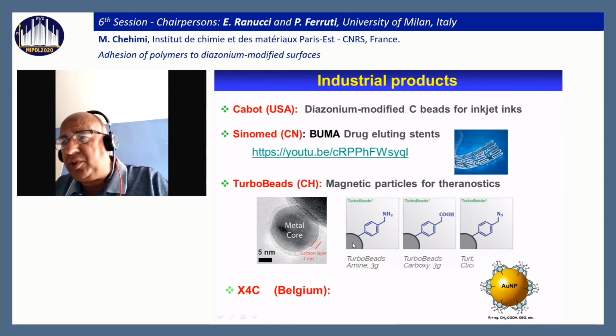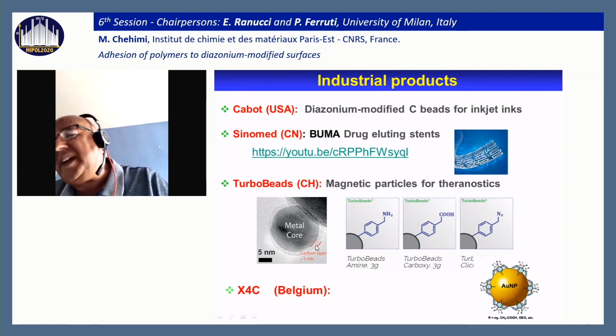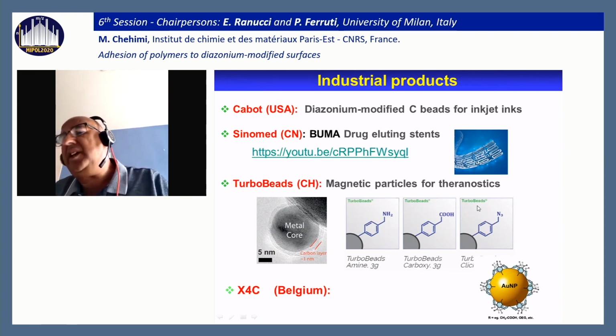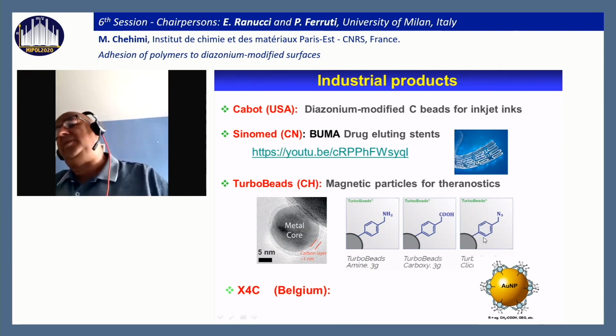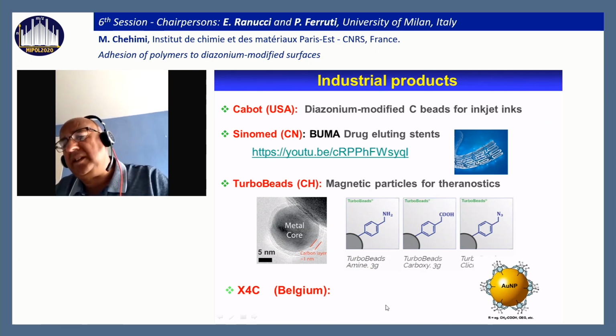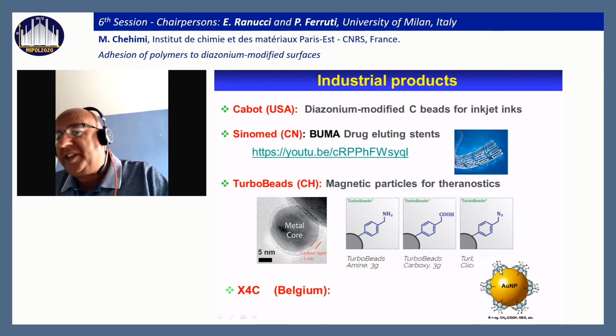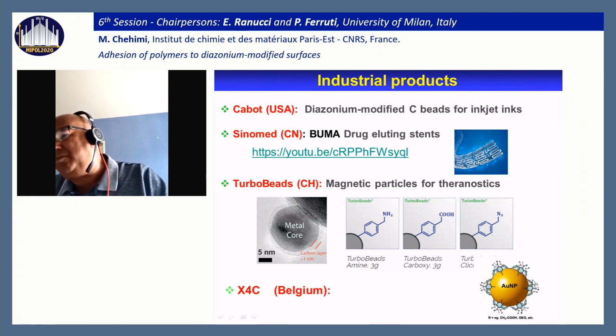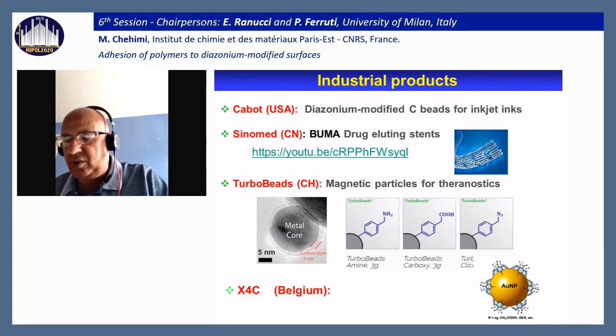Turbobeads in Switzerland produce magnetic nanoparticles for biomedical applications. They cap the magnetic nanoparticles with a very small carbon layer, because the carbon layer reacts spontaneously with diazonium salts and can provide functionalized aryl-capped magnetic nanoparticles. In Belgium, X4C is very well known for the production of calixarenes with four diazonium salt functional groups for the production of arylated surfaces or even gold nanoparticles.